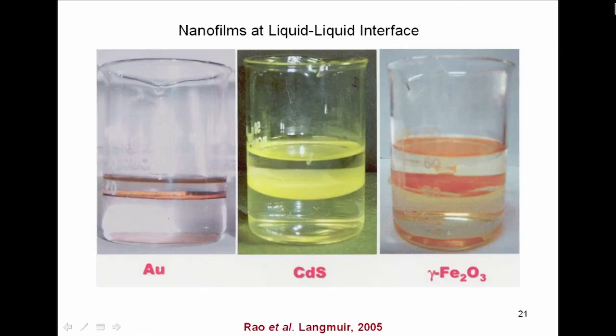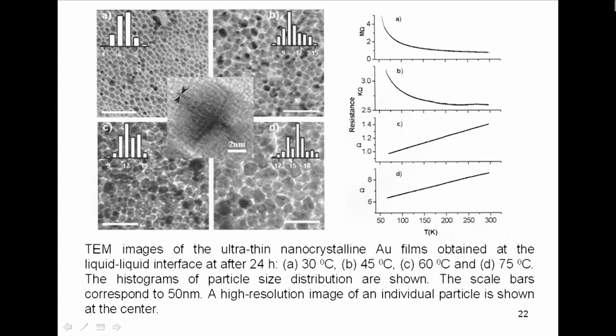And here is a very simple experiment. For example, if you take two liquids, like an oil and water, say benzene and water, they don't mix, but at the interface between the organic liquid and water, you can make very thin layers, which are two-dimensional sheets of nanomaterial. For example, I show nanocrystalline films of gold. The particle size can vary based on concentration, temperature, a number of things, and you can make beautiful nanocrystalline films at the interface. The interface being so thin, you always get a nanofilm. In fact, this technology has been used recently to make beautiful single crystalline films at the interface.